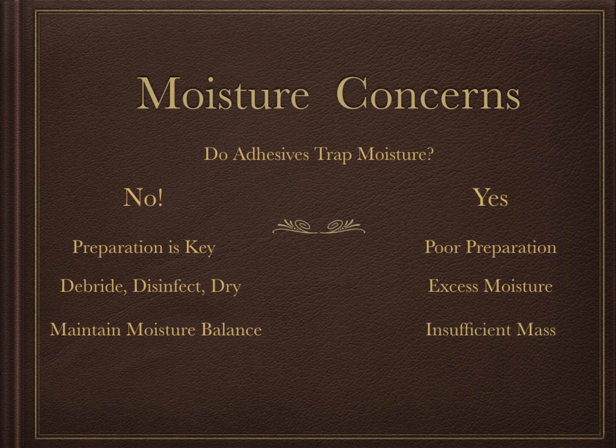And then again, there's insufficient mass. If you spread the adhesive too thin or dress it too thin, it doesn't have the strength, and it's more likely to become unbonded. Unfortunately, a lot of these things don't just become unbonded. Parts of them become unbonded, but they still stay there. So if they're in an unclean environment, now you've got a trap. You really want to avoid that.